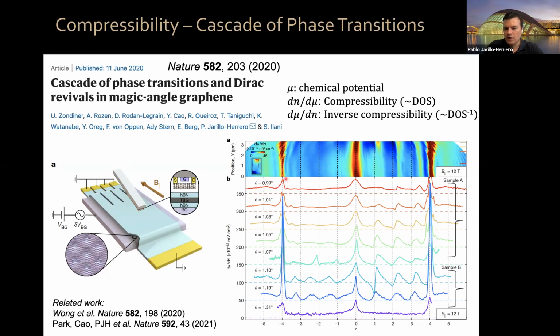You see there are only 3 basic features, a few others, but 3 features in the inverse compressibility as a function of filling factor. You have a peak at -4, a peak at 4, and a peak at 0. Again, because the inverse compressibility is like the inverse density of states, this is telling you that you have gaps at 4 and -4, and you have a Dirac point at 0. But if you go now to 1.3 degrees, above the magic angle, you have the same features, 3 peaks at 4, 0, -4. But if you go in between, in the magic angle range, let's explore here, for example, 1.13 degrees, you can see you have those peaks, but then you have also a whole bunch of other features.